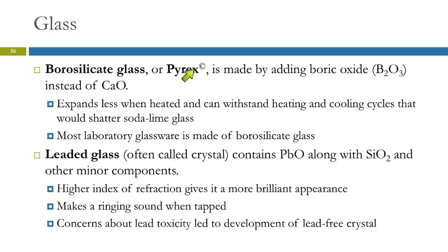Borosilicate glass — Pyrex — is made by adding boric oxide instead of calcium oxide. This causes the glass to expand less when heating, so heating and cooling cycles that would shatter soda lime glass do not shatter borosilicate glass. I had an experiment where students needed to heat something in a test tube — some were borosilicate (marked Pyrex) and some were soda lime. The soda lime ones had been put out by mistake, and one after another everybody's test tubes were breaking. Most lab glassware is made out of borosilicate glass — it is more expensive, but you need to heat the beaker without worrying it will shatter.